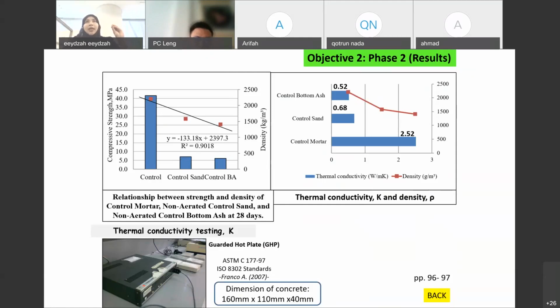Okay, Uniform Building By-Law, stating that to have a non-load bearing wall, you must have at least 5 megapascal. So at least we achieve that point, should be okay. Moreover, when I add POFA, it is actually a long-term strength. So it is high strength at later age. That's why with the pozzolanic behavior, it creates high strength after 40 days. So that's the reason I was thinking the strength is going to get better. That's the reason why I think it's okay. So I did achieve at least 7 megapascal.